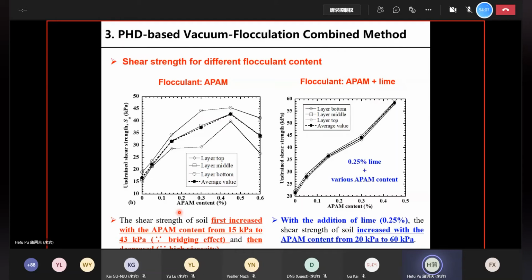And after some point, the strength will decrease with further increase of flocculant because the flocculant is some kind of polymeric material and has high viscosity. And on the right-hand side, on top of APAM, we further added in lime, because lime has both the effect of flocculant and the effect of binders. So when we're adding both flocculant and lime, the strength can be further increased. For the highest one, we can have 60 kPa of strength.